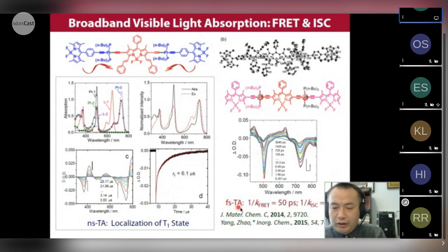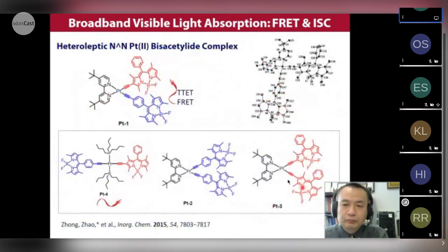With femtosecond transient absorption, we confirmed the singlet energy transfer takes about 50 picoseconds from the blue one to the red one. And the intersystem crossing of the red one will take about 1 nanosecond. For this one, maybe another painful work for students because this complex is not easy to prepare. We cannot prepare this one with a stepwise method.